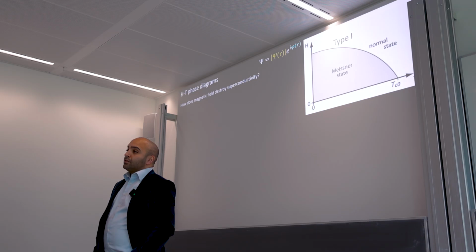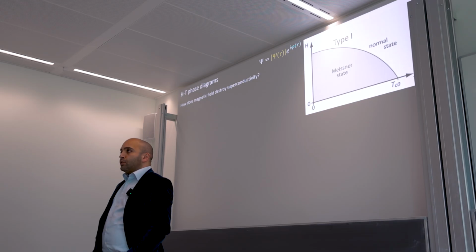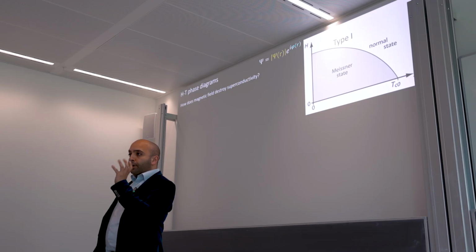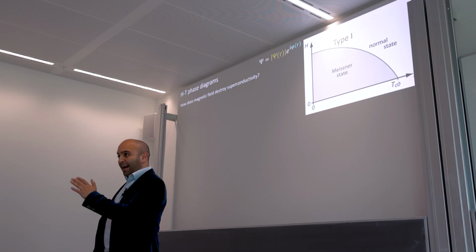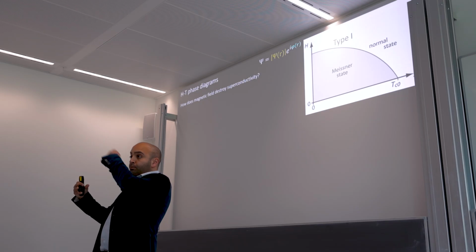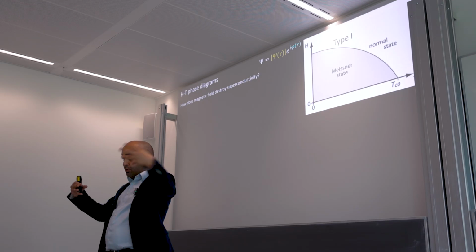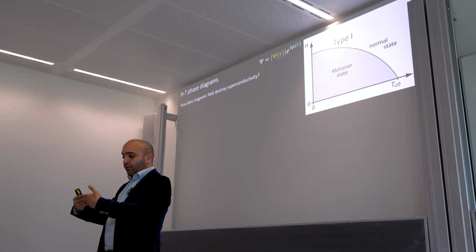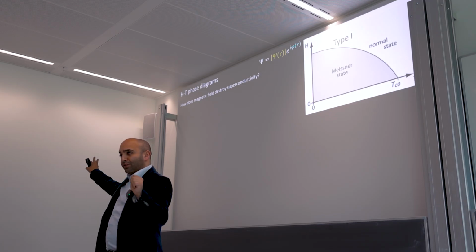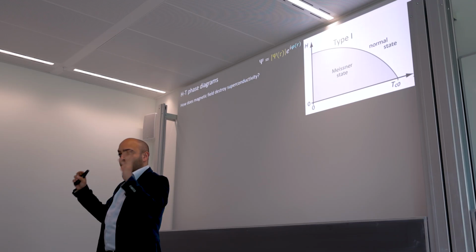Yes? The superconductor has a critical current that you can't go above. Sure, but as long as we stay below that, I mean, actually, in a bulk superconductor, your critical field and critical current are actually related. The reason you have a critical current is because the current that runs through your superconductor produces its own field, and this field at some point, so critical field and critical current are basically the same effect. Not in Josephson junctions, we'll come back to those later, but in a normal superconductor, that's the case.